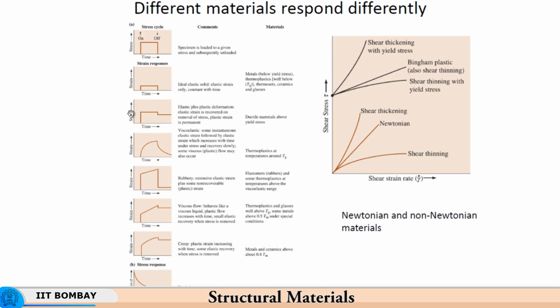Okay, you have hardening due to viscous effects. Now, here you are not talking about viscoelasticity. The difference between this and this is that here it is viscoelastic in nature, here it is viscoplastic in nature. So, there is a significant amount of plastic strain that is retained over here. So, you have thermoplastics and glasses above the Tg, and so they become a kind of viscoplastic. And so, here also you have a similar situation where this rise in strain rate is non-linear in nature.